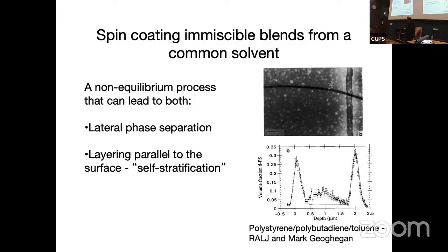The surface effects mean this phase separation can be driven, in this case, just by the solvent being removed. What's going on here is you're just taking a mixture of two polymers in a solvent, you spread it out on a surface, so you make maybe a 10 micron layer of material, and it just spontaneously layers. So you just get, in this case, a three-layer system.